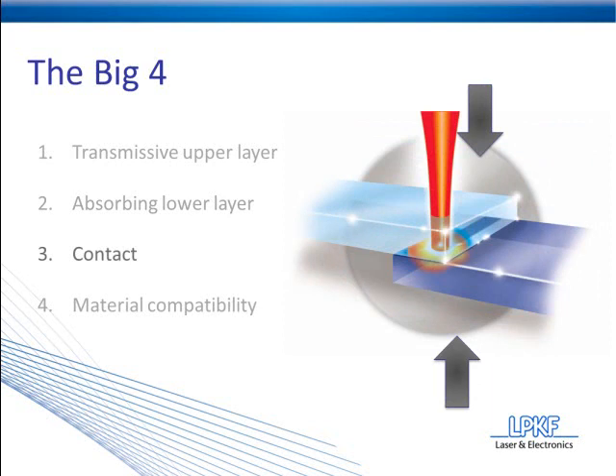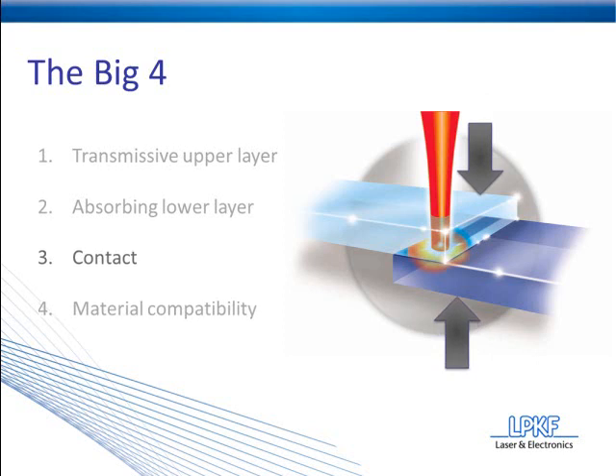The problem you run into is that it's only being absorbed by the lower layer. So in order to get the upper layer to heat and become molten to create a weld, you have to transfer that energy from the lower layer to the upper layer. Now this is done through conduction, and contact is going to ensure that. Now, typically contact is achieved by building the parts to fit well together naturally. However, to ensure perfect contact, pneumatic clamp tooling will be used throughout the process.